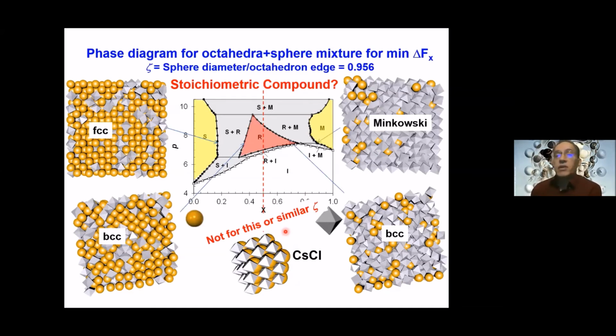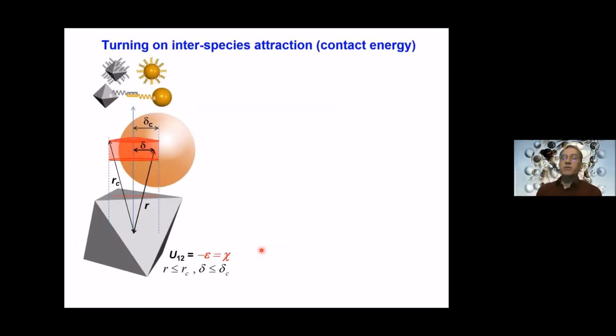And that was a little bit disappointing perhaps, but not very surprising in the sense that to get something like this, it has to be true that each component really prefers to be contacting the other component. You can see that the octahedra will be touching basically spheres, not octahedra. So that clearly needed some strong selectivity to do something like this. So we thought, oh, that's time to turn on our energetic attraction. So I'm going to now change epsilon or chi.